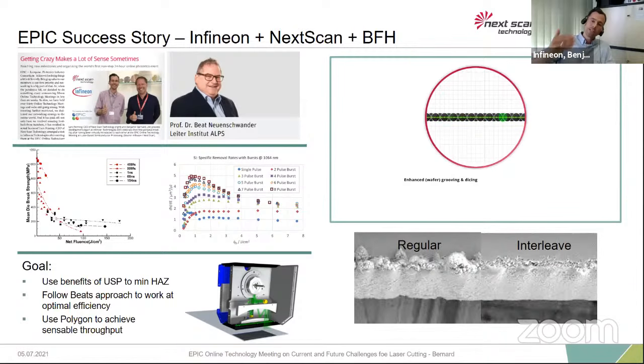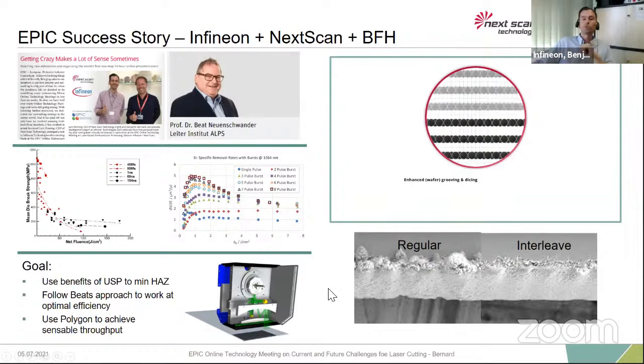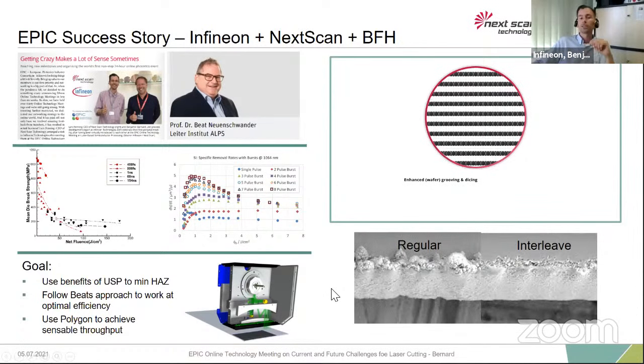And I want to show you one example of what is doable, a processing called interleave. With each second pulse you leave open, and then on the next overscan you fill that gap. That means you have double the amount of overscans, but it's very nice for the heat management. And you can see here the same parameter settings. One time is creating a lot of melt, and with the interleave approach, we're able to reduce this heat effect and melt quite a lot.